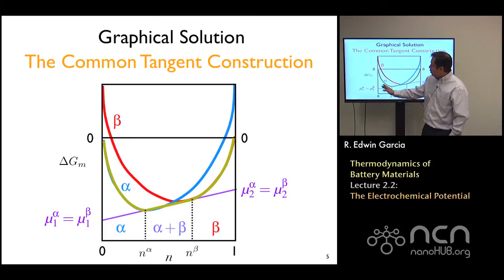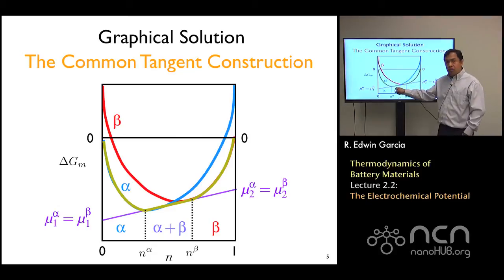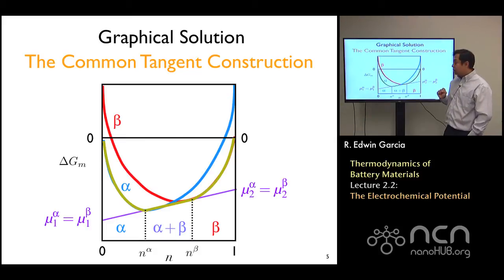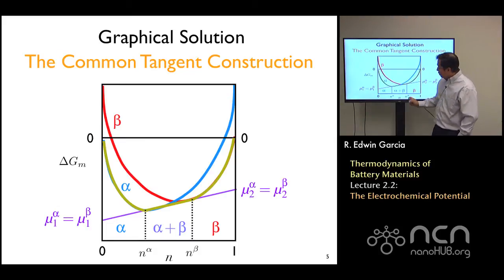So you can think of, on one side, the chemical potential is varying, then it hits this regime where the chemical potential is fixed, okay? It leaves that regime, and then the chemical potential changes again, okay? As a result of that, what you have is a region where you will have that voltage be flat, okay? Specifying with that a concentration regime that you can use as a material potential if you manage to maximize its width.